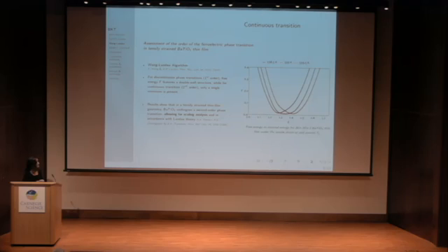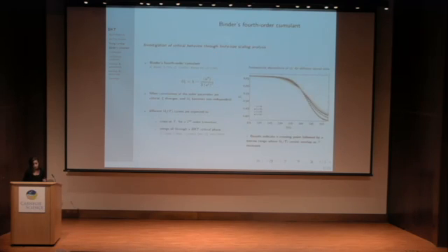And we find that the structure remains with a single well at and around criticality, which confirms the continuous order of this phase transition, and which, most importantly, enables us to perform finite size scaling analysis, since such analysis is based on the divergence of the correlation length.